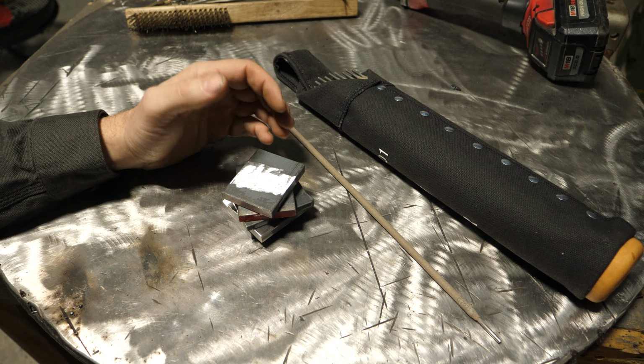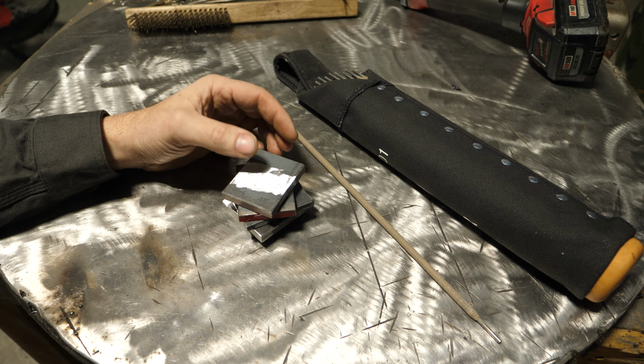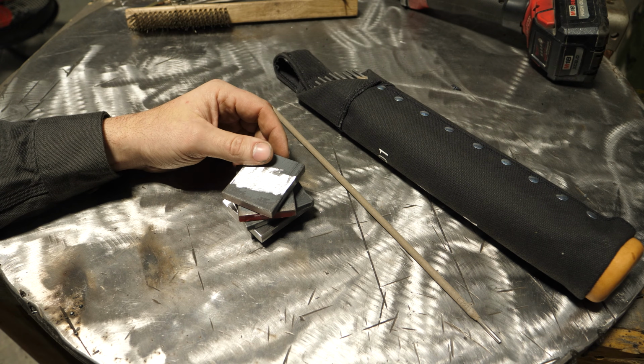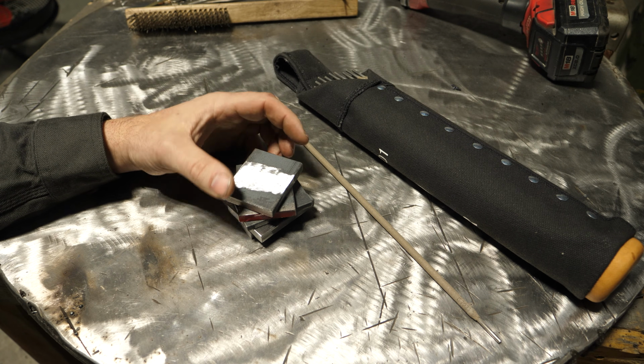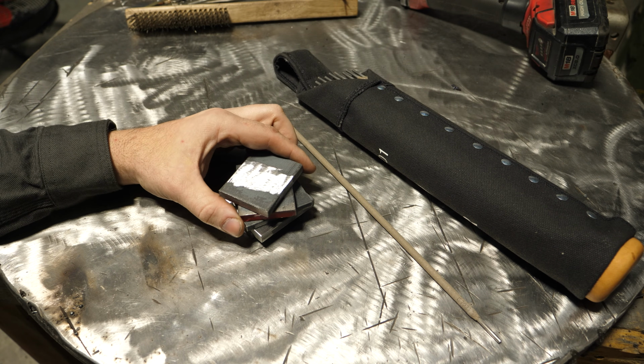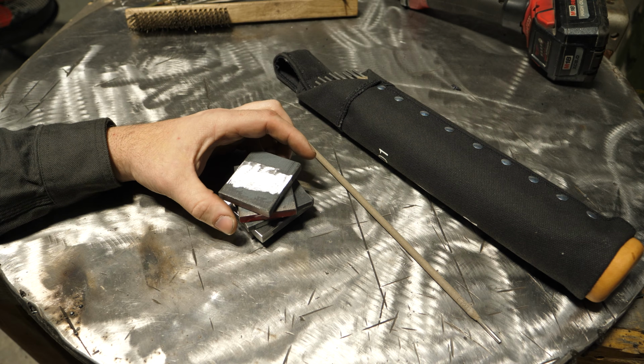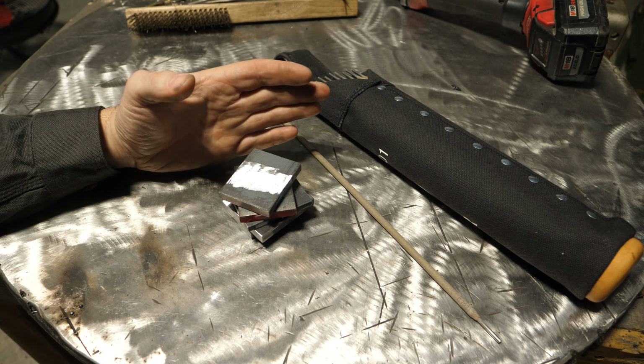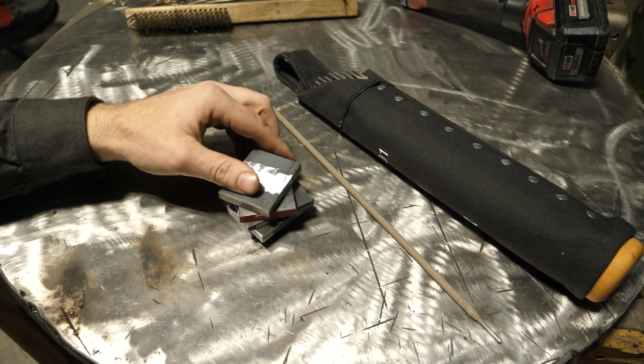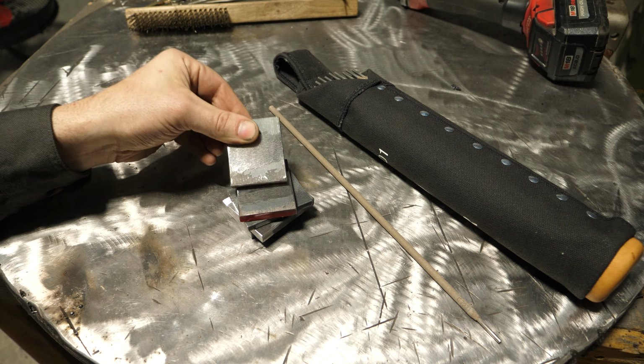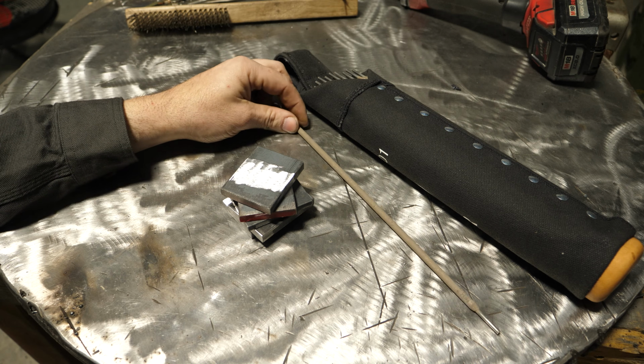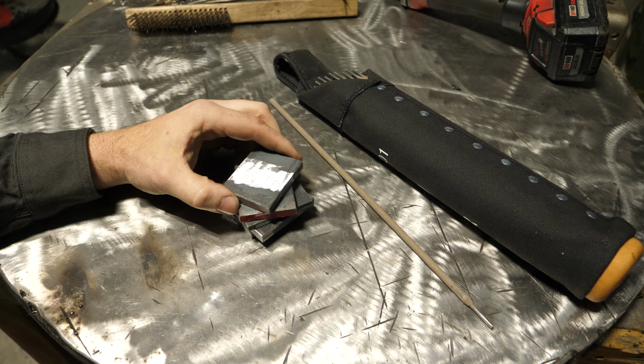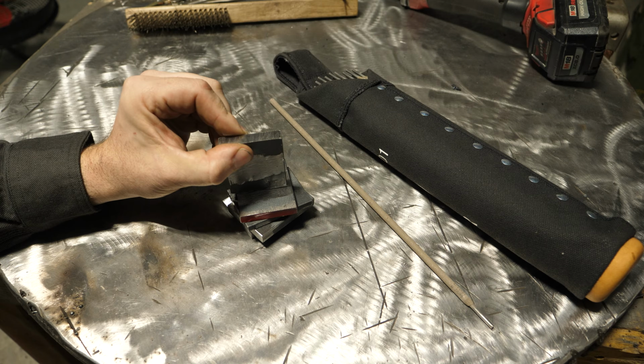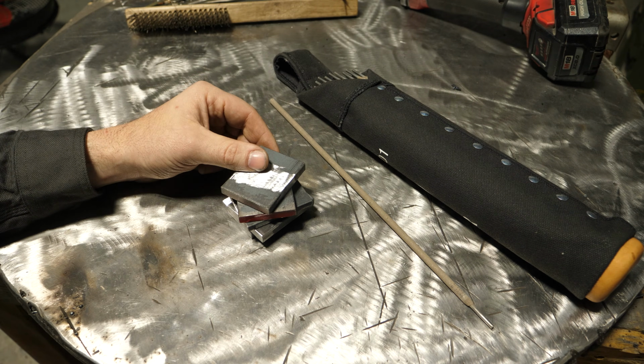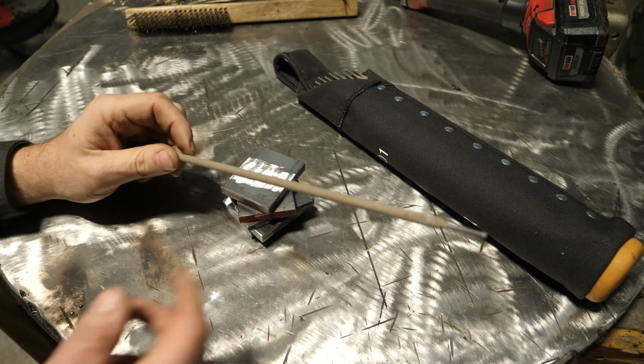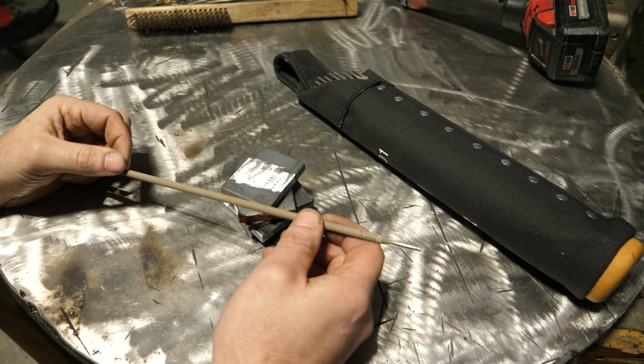Now, in the previous test videos, 70-18 has passed on a bend away from the face, so a tensile strength test. ER70 MIG has. However, 70-14 rod did not. 60-10, 60-11, 60-13, all of those have failed on bend tests away from the face. So by testing 70-24 today, we're going to see if that also indeed fails when bent away from the face of a weld. The particular rod I'm going to be using today is Blue Demon 70-24.